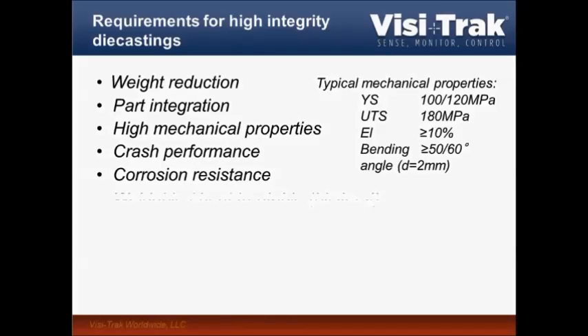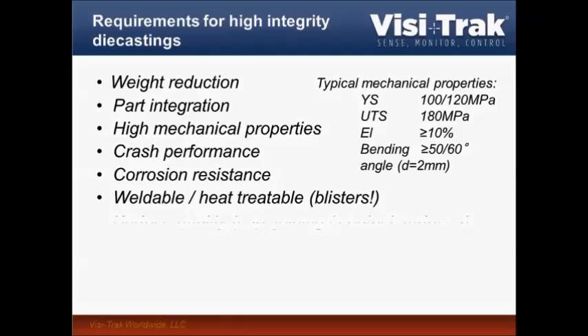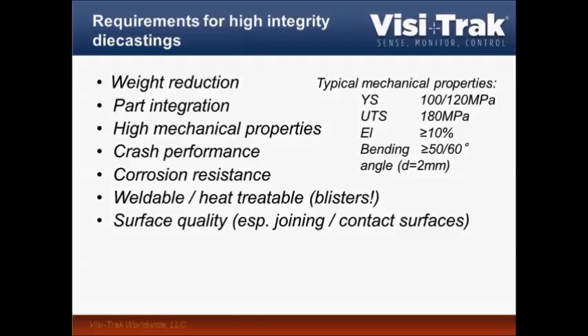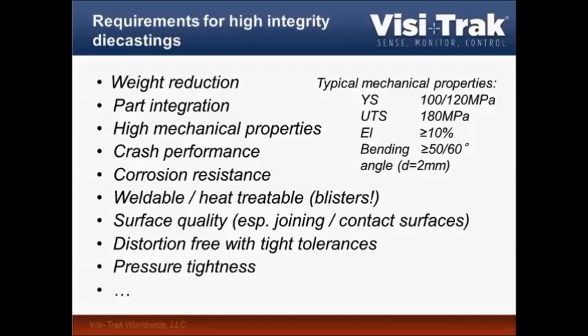Then of course corrosion resistance in the car body structure. Very often they have to be weldable and they have to be heat treatable, and anyone who has put a die casting into a heat treatment furnace knows that the big challenge here is blisters. Then that leads to surface defects, but the surface quality in general is a big requirement, especially in the joining or contact surfaces. The parts have to be distortion-free with very tight tolerances. That is one reason why we don't want to do die casting for these parts. Some have to be pressure tight, etc.